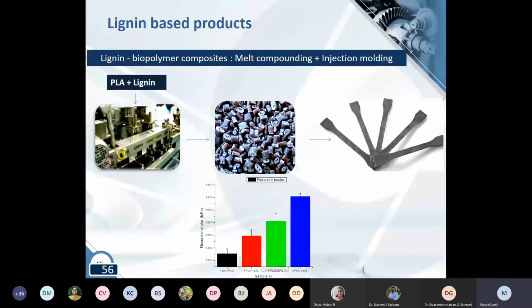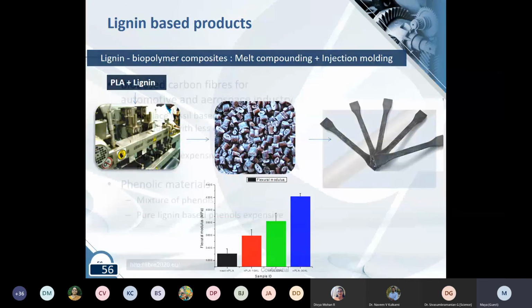The problem with lignin is that there is an issue with dispersion of lignin in biopolymers, and one would have to use coupling agents or compatibilizers to improve the dispersion. So though we notice an improvement in modulus, that is mainly due to the volume content of lignin. In order to get good tensile strength, one often has to use coupling agents.